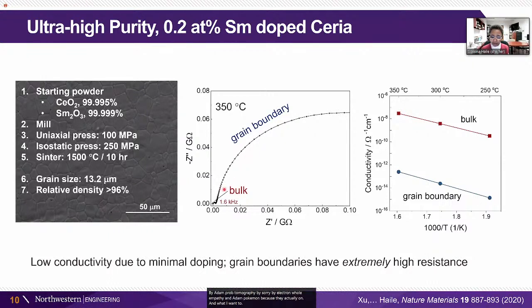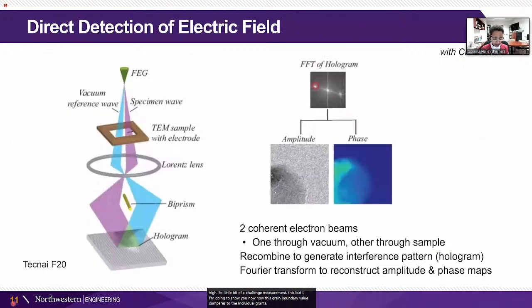And what I want to point out here is this is an impedance measurement. And because this material is so lightly doped, the impedance is extremely high. And this little arc here is the bulk impedance. This large response here is the grain boundary impedance. We convert that to actual values of conductivity. And we can see here that the grain boundary impedance is extremely, extremely high. So a little bit of a challenge to measure this, but I'm going to show you now how this grain boundary value compares to the individual grains later on.